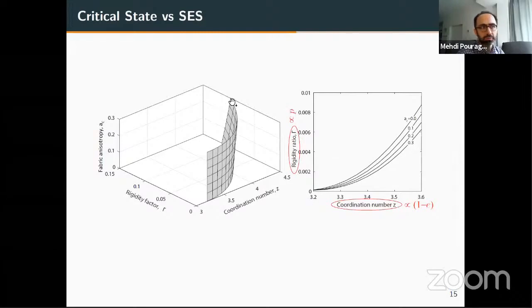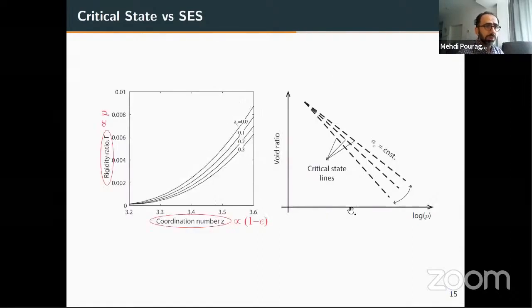It has been shown, and we can show, that when this state is reached, the coordination number has a one-to-one relation with void ratio or the porosity. So we can directly say that these lines of constant fabric anisotropy can be looked at as different critical state lines in the space of void ratio and P with different fabric anisotropies.